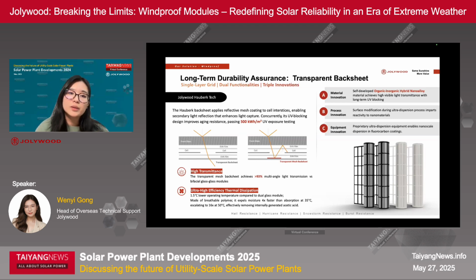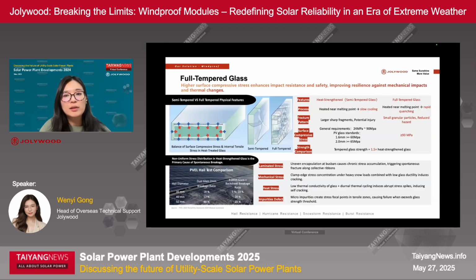With the help of the transparent backsheet, now we can use a thicker front glass to protect the module. With a thickness over 2.5 millimeter, the glass can go through the fully tempered process, which means there's a higher surface compressive stress, which can enhance the impact resistance and make it more resistant against all kinds of mechanical impacts and also thermal changes, which the 2 millimeter front glass for the dual glass module cannot achieve.